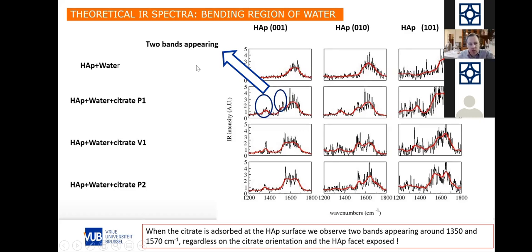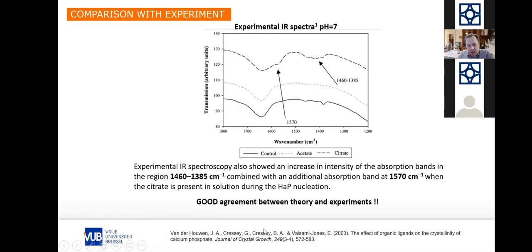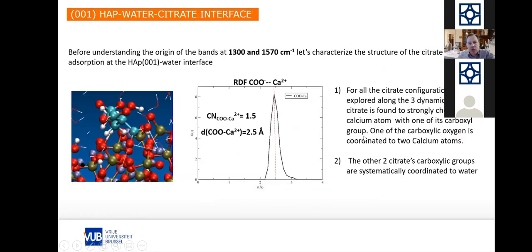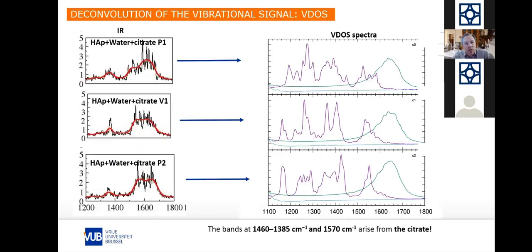In fact, we see two bands appearing, about the 1570 and the 1385 region. And we recover this data, but the question is now, where does it come from? What we've seen is that thanks to the radial distribution function, we see the distances and the interaction between the cation, the calcium, and our anionic group. We can in fact isolate the different vibrations. We call that a vibrational density of states.